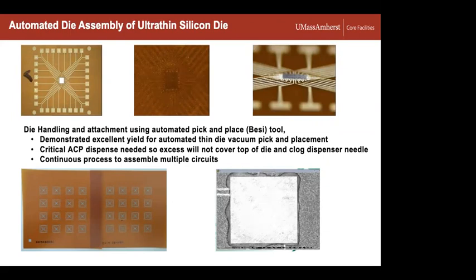And on the right, we show kind of an angular image where you can see how thin that particular silicon die is. Lower right is just a top-down image of that. So you're seeing that the adhesive is now just pushing out beyond all edges. And so that's just the right amount. Problem is, if you get too little, you don't get good attachment of all the leads. And if you get too much, it comes up on the top and starts to impact your vacuum pick tool. So those are all issues that we had to work through, understand, and develop methods to improve those.